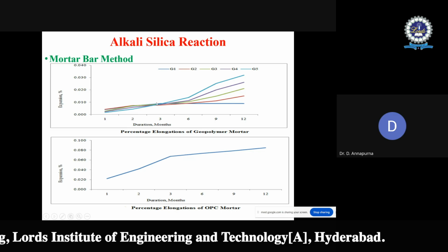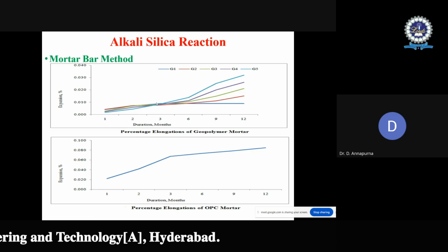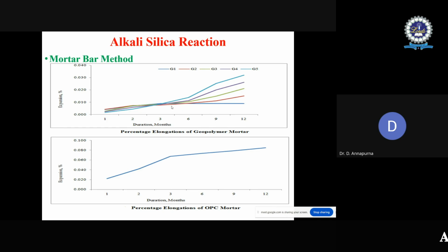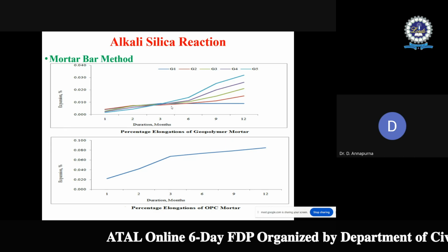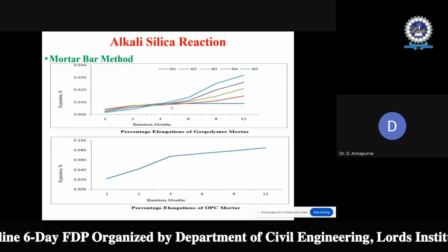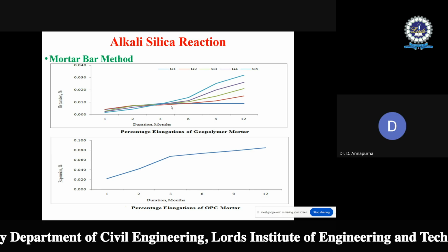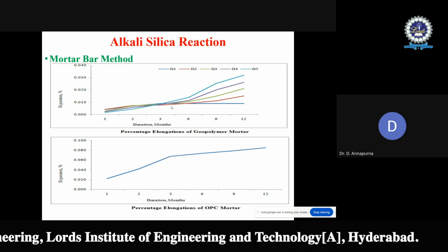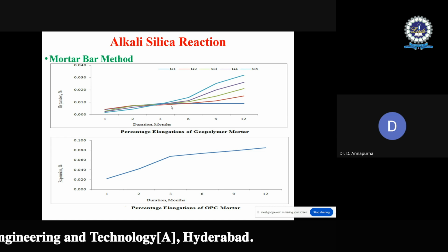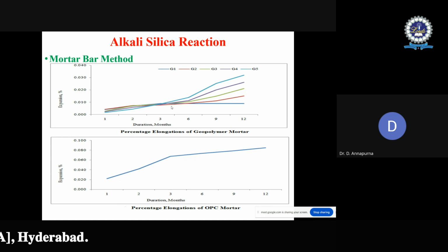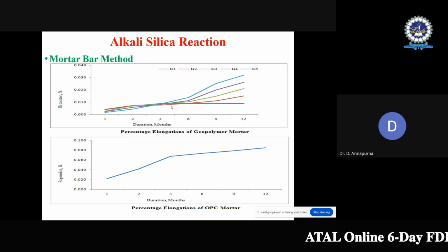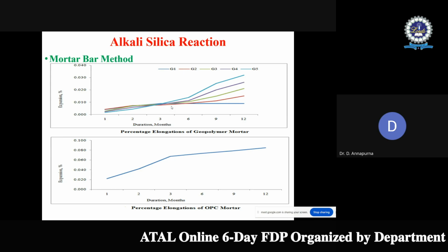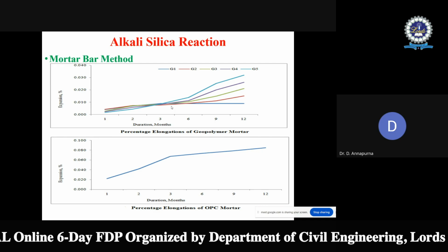As per the IS 2386 Part 7 code, if the 6 months elongation is within 0.06%, then the material can be stated as not reactive. Even if it is added with reactive aggregates, alkali silica reaction will not occur, so it is not potentially deleterious. It is called deleterious as per the standard otherwise. And as per ASTM standards, the 12 months elongation should be within 0.04%.